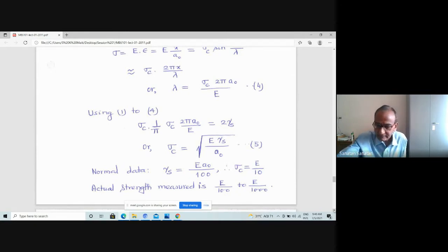So this was first calculated by material scientists. What is the theoretical strength of a material? For any material, you can calculate the theoretical strength using the normal data for surface energy, and this critical strength comes out as modulus of elasticity divided by 10. But for most engineering construction materials, the strength is in the range E by 100 to E by 1000. Look at that. Theoretical strength is E by 10, but the actual strength of the material is E by 100 to E by 1000. So it is 10 to 100 times less.